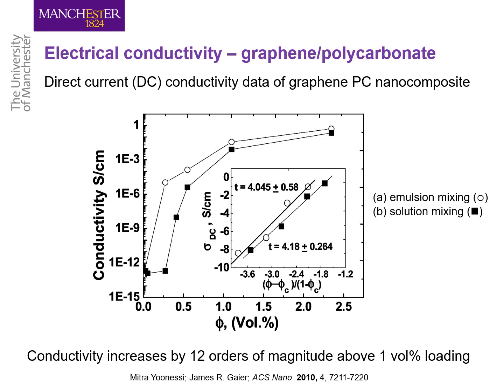The electrical conductivity increases by 12 orders of magnitude for a polycarbonate nanocomposite with 1% by volume of graphene platelets. The thermal conductivity also improves, in addition, of course, to mechanical properties like stiffness and strength.